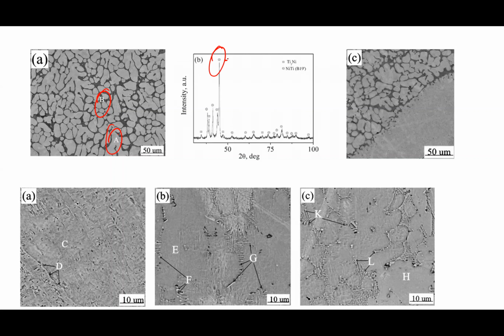which is available. So the quantitative analysis of the SEM image of the first layer was performed by the system. We could see the fraction of NiTi phase which is available was about 75 plus or minus on an average. A large amount of Ti2Ni phase was observed in the first layer, and the precise interface was visible between the first and the second layer.